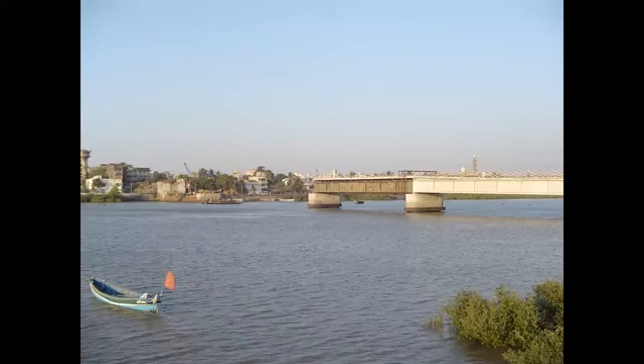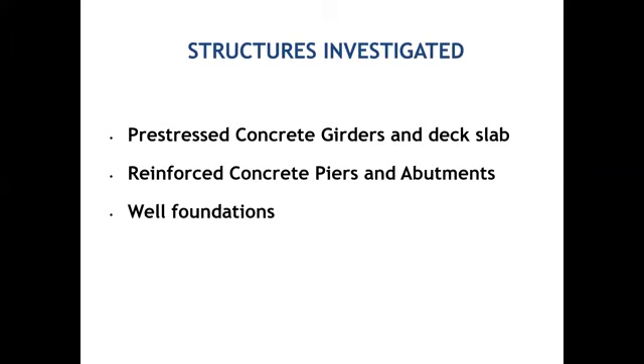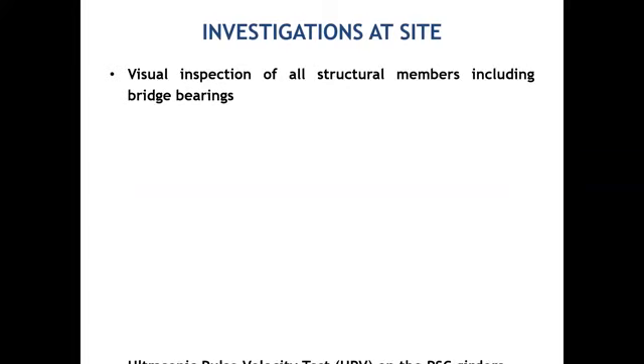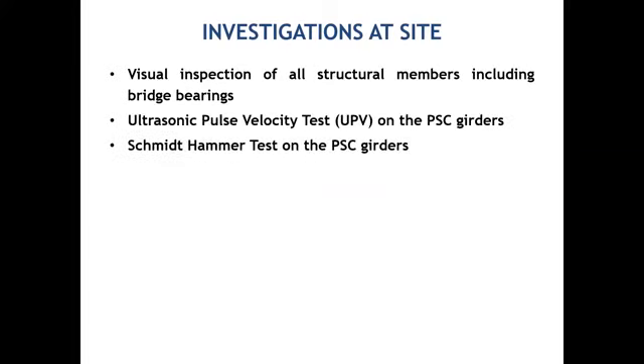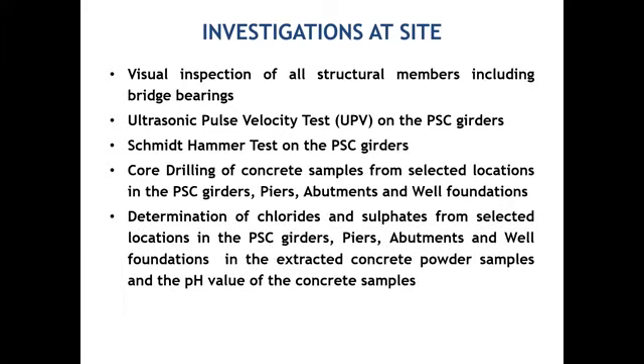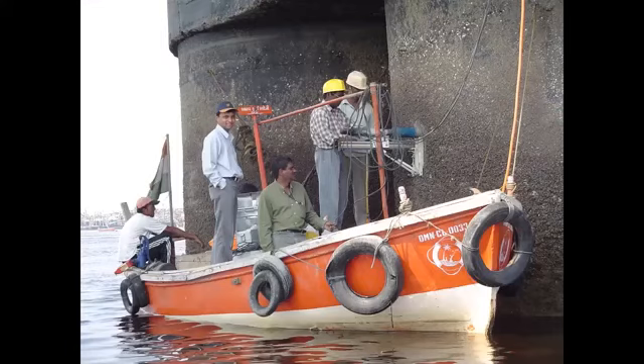Next, condition assessment of a bridge. This bridge, again, was washed off during a flood, and they had other related issues. It has a pre-stressed concrete girder and deck slab, and reinforced concrete piers and abutments. A well foundation was adopted. Visual inspection was done, including the bridge bearing, ultrasonic pulse velocity, rebound hammer, core extraction, and determination of chlorides and sulfates. As it is a PSC girder, your regular core extraction cannot be done. So a special system was adopted by SCRC to find out the loss in pre-stress. This is how the testing was done.